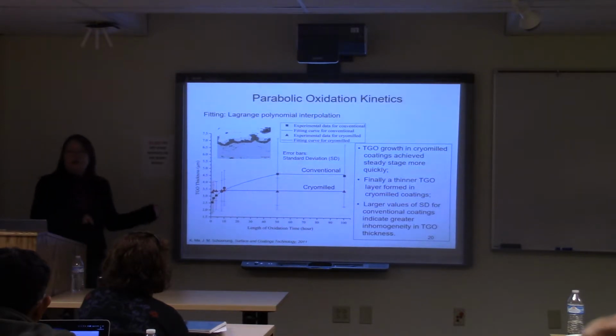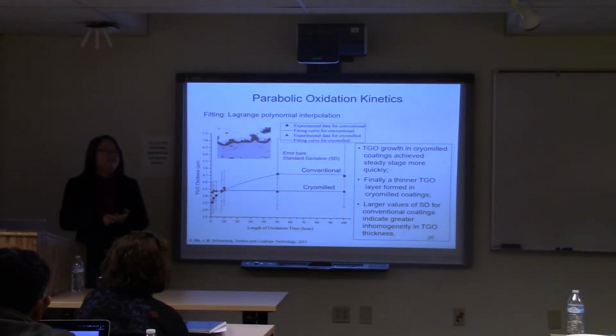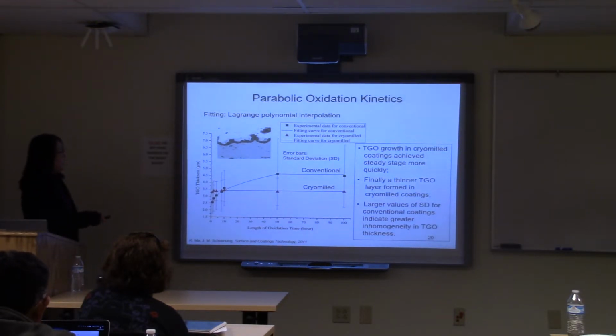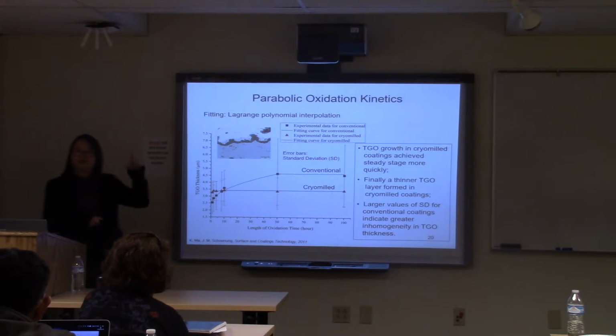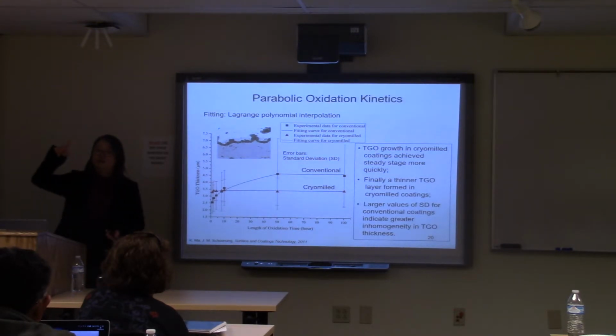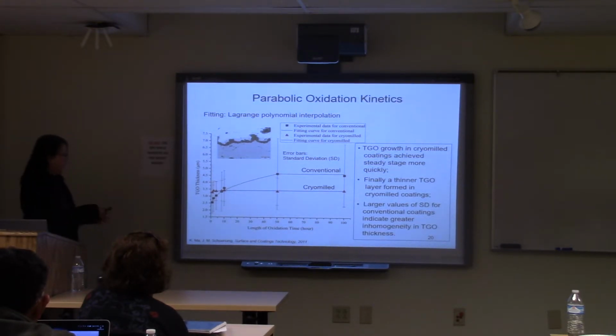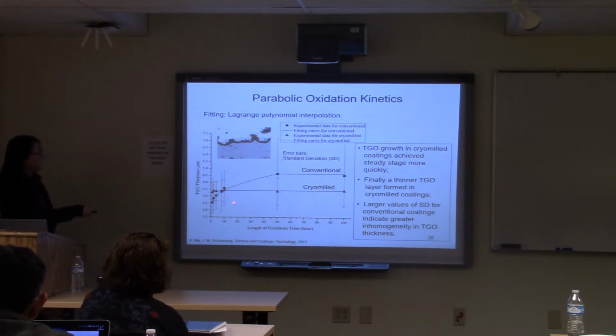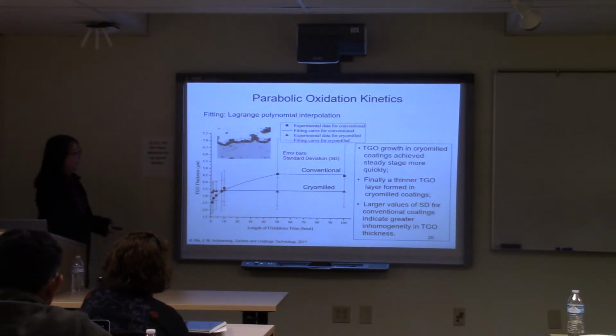And the thing I didn't show here is the XRD and the EDS mapping, which help me to understand what's the composition of the oxide layer. But coming back here, if we plot the average thickness with error bars, which is the standard deviation, giving you the idea about how homogeneous the TGO layer is across time here. And you will see the TGO growth in the cryomilled coating achieves the steady state very quickly, and it ends up with a thinner oxide layer here.